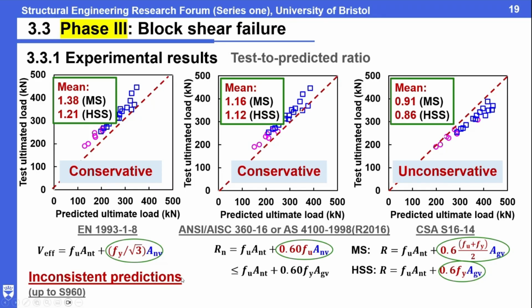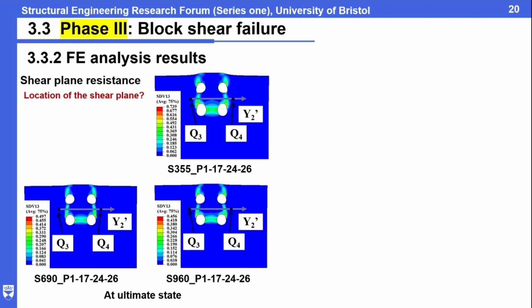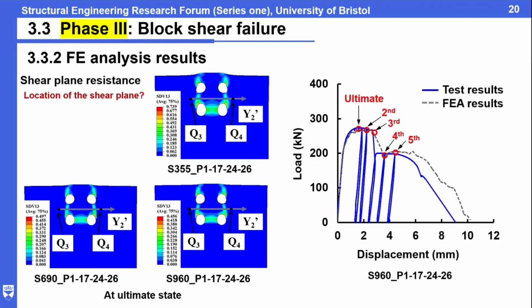The main reason is the definition of the shear plane resistance. So is it possible to find a universal one? We need to further investigate the failure mechanism first, and based on the mechanism, then check the design philosophy, right? So let's see the failure mechanism. Let's see the shear plane resistance. It consists of the area and the strength, right? First, let's see the location of the fracture plane on the shear. This is a loading and unloading progress. We extract the typical one, and then plot the stress development state at each stage.